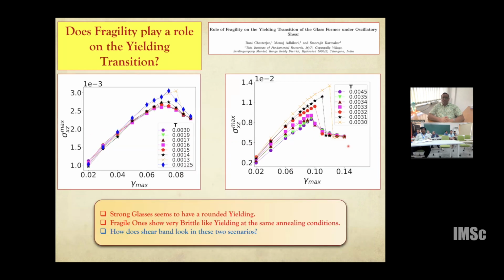And then we asked this question: is there a way to understand it? And what we feel is the scenario lies in the shear band. So if you plot stress versus strain, you see that in a strong glass, even if you have reasonably well annealed glasses, you still do not get very clear-cut shear band like drops. But for a fragile glass, you get a very clean shear band formation. So we are pushing ourselves a bit more along this line, and we have to simulate much larger system sizes to get a clean shear band and to study whether indeed there is a difference in the shear band between strong and fragile glass formers. We don't have an answer to it yet.